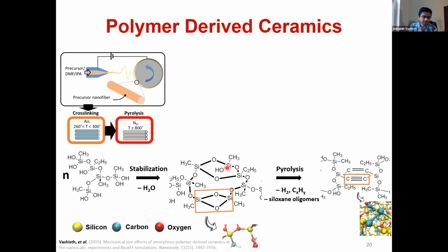Now, when you put this stabilized polymer compound into a furnace, and you cook it at really high temperatures, close to 1000 degrees Celsius in inert atmosphere, what we call pyrolysis, you have a bunch of hydrocarbons, siloxane oligomers, and H2 that evolve. And finally, you have a structure that has carbon triple bonds, carbon double bonds, and more silicon-carbon bonds, and it makes a very strong ceramic structure. And this is a very brittle, very strong ceramic structure.